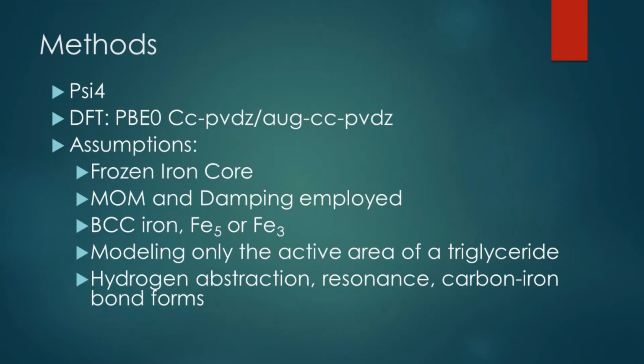To aid convergence, core iron electrons were frozen and damping was set to 5%. The Maximum Overlap Method, MOM, was turned on after 80 out of 100 iterations, which helps greatly with oscillating values. These parameters, along with the optimized geometry of the molecules, were used in the Psi-4 suite of programs to calculate the energy of each state.